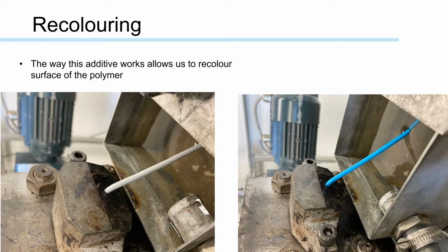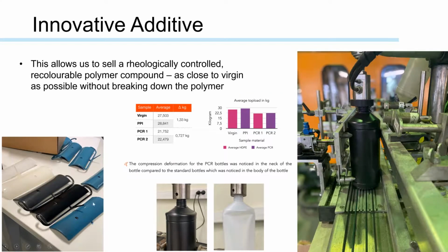So that black polymer you saw before was our rheologically controlled polyethylene. This is our polyethylene with master batch added on top. Now these colors appear very bright, and that is what it's like when it comes out hot. And as the polymer cools, the color does become a bit more pastely, like what you can see on the left-hand side here.